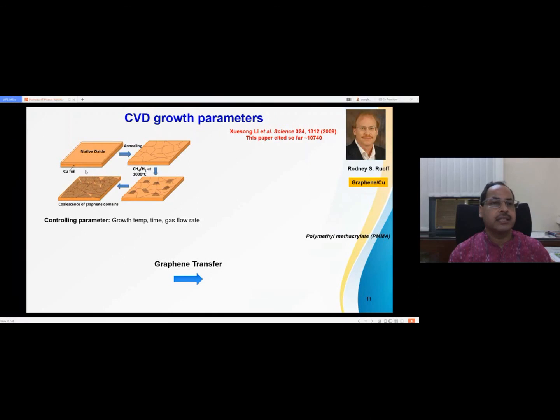Now coming to the CVD parameters. What do you do generally? You get a native oxide. When you take it from the supplier, it is copper oxide, so you etch it and remove the oxide layer, so it has only copper, and then you anneal it. There is grain growth, and then when you do your CVD process, you can see the carbon atoms nucleate near the grain boundaries, and when you increase the time, the graphene domains coalesce, and you can get single layer graphene. The probability of getting monolayer graphene is 90 to 95% in the case of graphene on copper. So the control parameters are very important. You have to play with growth temperature, time, and the gas flow rate.